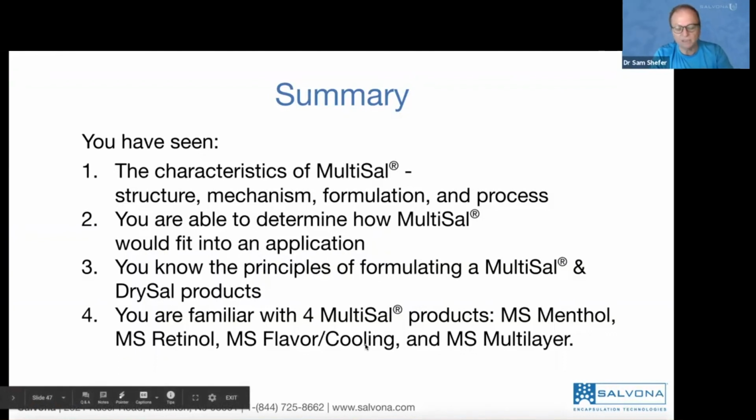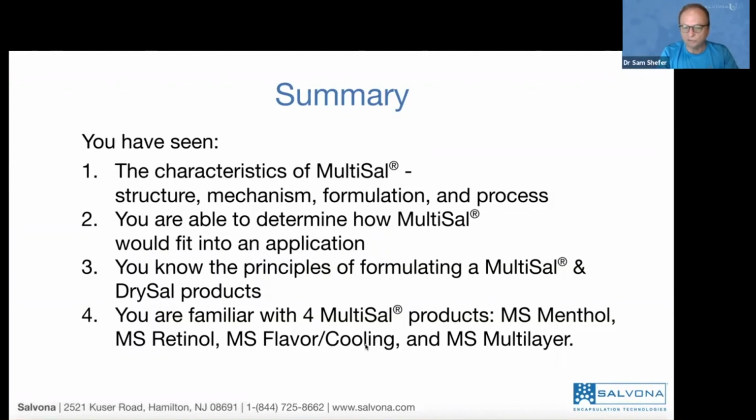We many times don't explain too much about this, but you understand that you cannot formulate a stable formula with acid and also with peptides. The peptides will denature because of the acid. And some of the brightening ingredients require a higher pH than the acid can offer. So there is no way to put them all together. The only way to do it is to encapsulate them and then put them in different compartments in one single ingredient.